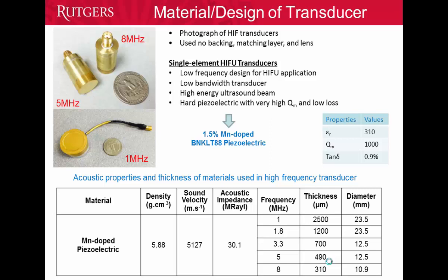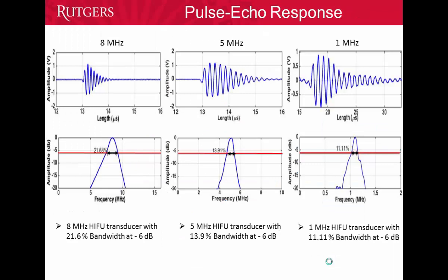These transducers are single-element transducers. We didn't use any backing layer, and we didn't use any kind of focusing technique. In this table, you can see the properties of the transducers: the frequencies of 1, 1.8, 3.3, 5, and 8 megahertz, and the thickness and diameter of the transducers.